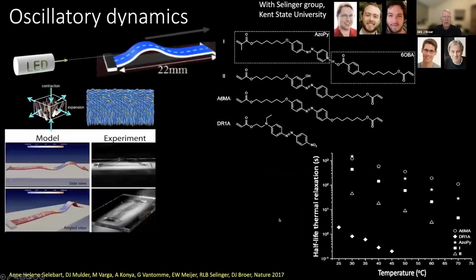I'm now close to the end of my presentation. I would just like to show a few examples of other motor molecules. Then we go from surfaces to more freestanding topics. This is work that we did together with the group at Kent State University, with the Selinger group, and also with the group of Broer at the time. In this case, we take a bandlike film of our material, where the film has a splayed structure, and we expose it with an LED lamp. At the position where we hit the film, it wants to bend away from the light, but because we fix it at both ends, it tends to bend up at another position, which then will be hit by the LEDs.